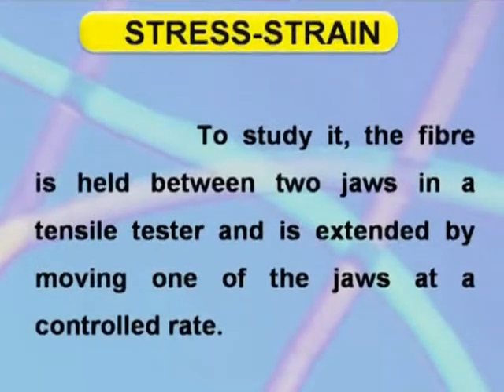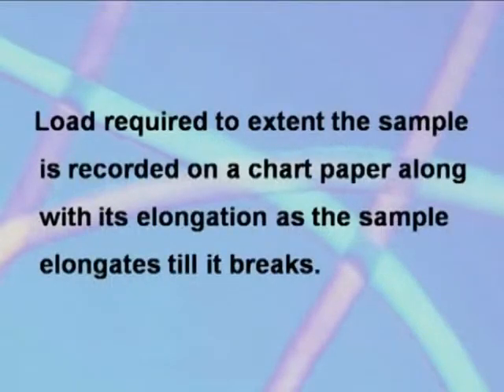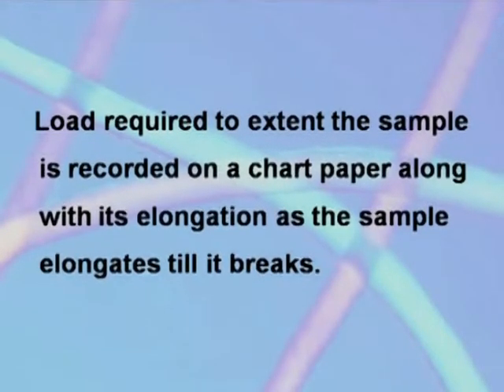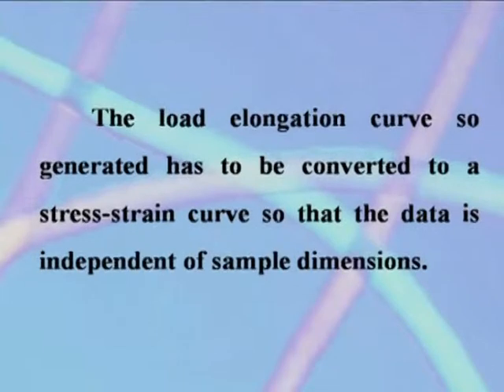Stress-Strain. To study it, the fiber is held between two jaws in a tensile tester and is extended by moving one of the jaws at a controlled rate. The load required to extend the sample is recorded on a chart paper along with its elongation as the sample elongates till it breaks. The load-elongation curve so generated has to be converted to a stress-strain curve so that the data is independent of sample dimensions.